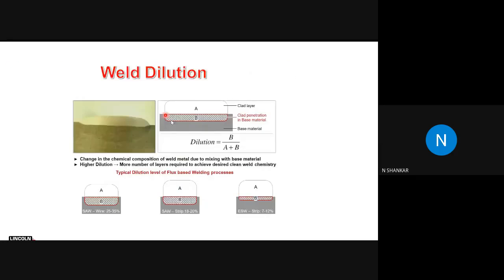Dilution is defined by the penetration you achieve divided by the total weld height. In cladding, you want only the material to be bonded, not penetrating too much, because this layer has to provide the corrosion resistance or thermal resistance on the inside of the wall. So you don't need penetration. Less penetration or less dilution is better in cladding. That is why you want much lesser dilution in cladding applications.